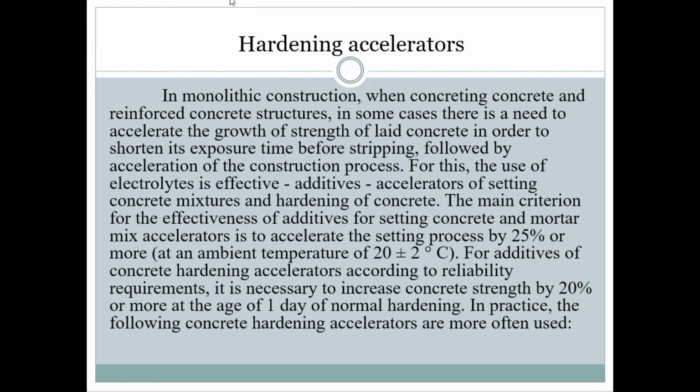For additives of concrete hardening accelerators, it is necessary to increase concrete strength by 20% or more at the end of 1 day of normal hardening.